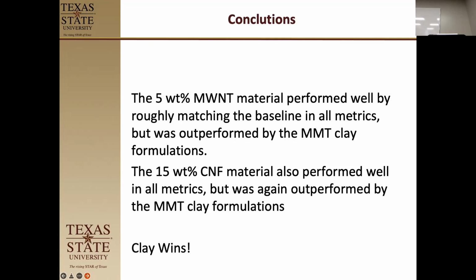So obviously, not thinking about the heat transfer of the carbon nanofibers was probably their biggest problem with this. The multi-wall carbon nanotubes, if they're short persistence length, are not going to transfer heat as well, and so that might be why it performed better than it did. But the montmorillonite clay has a low thermal conductivity, which led to that higher resistance to heat flow, which led to higher properties.